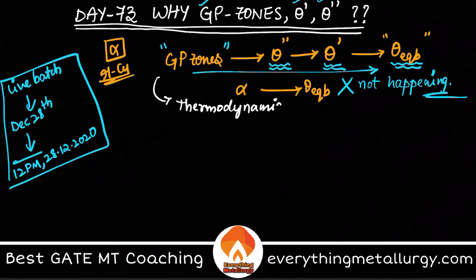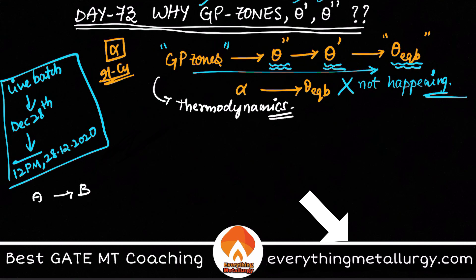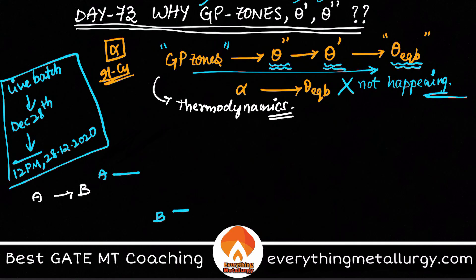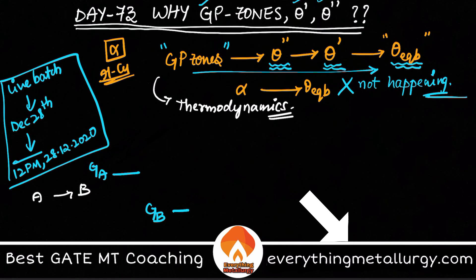Let's talk about the thermodynamics of this sequential transformation. For any transformation — let's say A converting to B — B is nucleating from A. We have a supersaturated solid solution after quenching, and it tries to reject out the excess solute. In terms of energy states, if G_A is the free energy of A and G_B is the free energy of B, A wants to go to B because B has less free energy. Any transformation aiding in minimizing free energy is spontaneous and favorable.